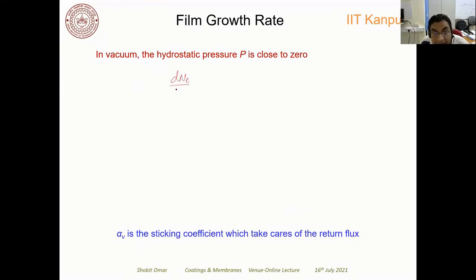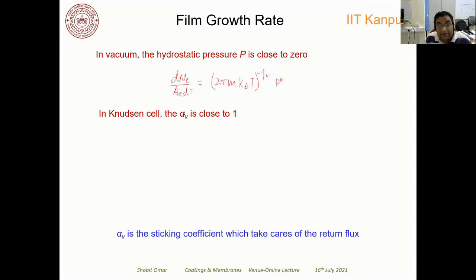dN_E/dt, the evaporation flux here, and it is given by (2π m k_B T)^(-1/2) P*, where k_B is the Boltzmann constant, T is the temperature, m is the molecular weight, atomic weight you can say. Then you have P*, because P is going to be 0 when you have a vacuum. Okay, and in Knudsen's cell, that is what I was saying, Knudsen had designed a cell where the sticking coefficient is almost equal to 1. So in that particular case, the sticking coefficient is going to be equal to 1. So what you have is (1/A_E) dN_E/dt equal to (2π m k_B T)^(-1/2) P*. Okay, so this is what you will have.